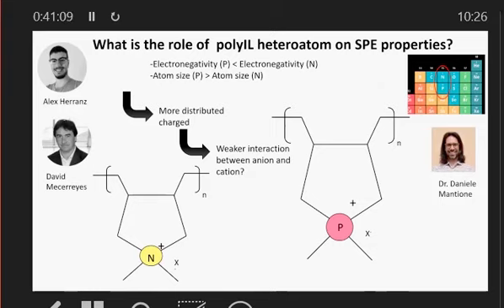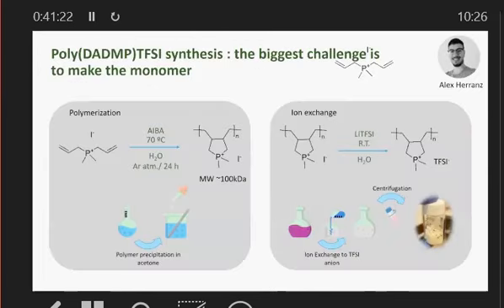And the idea being phosphorus being bigger, same periodic table, bigger, weaker interactions, it may change how the behavior of the system translates in ion dynamics and ion structuring. Very quickly, I'm not a synthetic chemist, but I want to show you basically the first most difficult step is making this monomer. This here has taken Alex the best part of 3 or 4 months or more to make and purify. It's a very hard thing to make, but it's doable. He's made a bulk amount of it now. Then you can polymerize that to make the polymer.